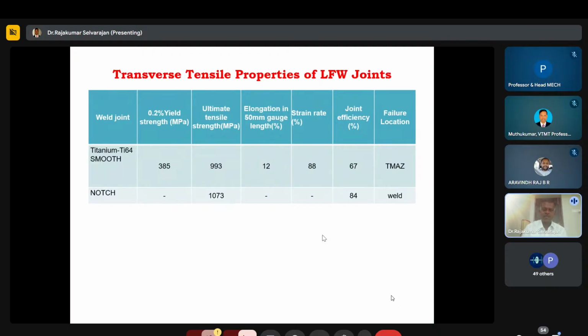Whatever the tensile properties are, they are recorded in this table. As I already told, we achieved the maximum tensile strength of 993 megapascal and notch tensile strength of 1073 megapascal, and the joint efficiencies we are obtaining are 67 and notch 84. The weld failure region is the thermomechanically affected zone, and the notch is in the weld region.